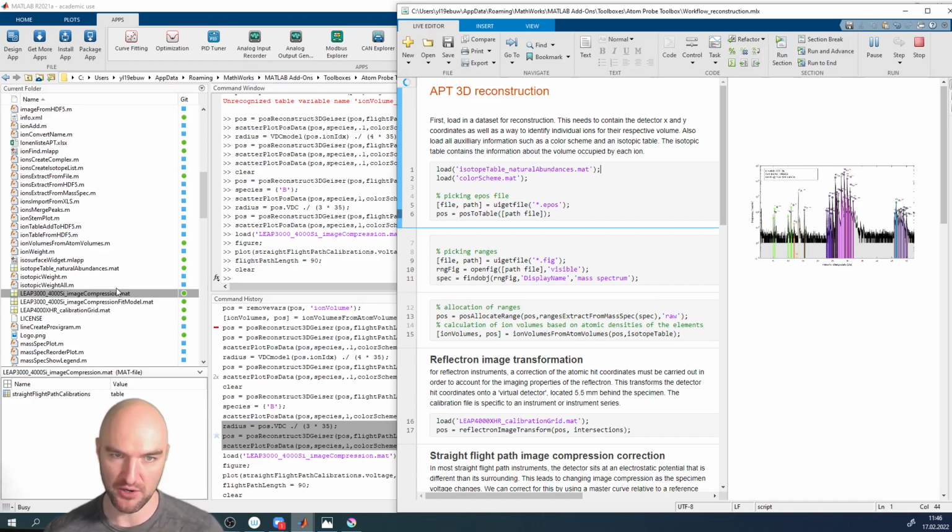Most of the time during the reconstruction is spent accumulating the volume of the atoms, creating the cumulative sum, because it cannot be parallelized easily. If you create a cumulative sum of the volumes beforehand, you can speed it up significantly. So you can do 10 reconstructions a second, on the GPU 100, 1,000 reconstructions per second, and then just look up which one is the best one.